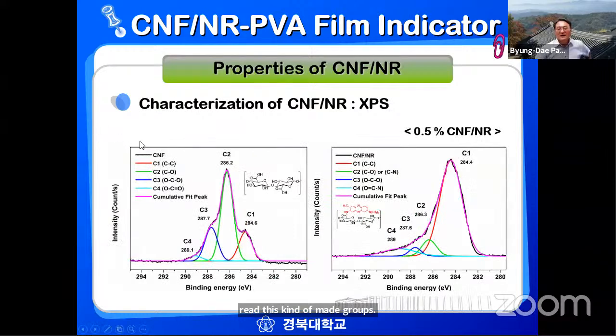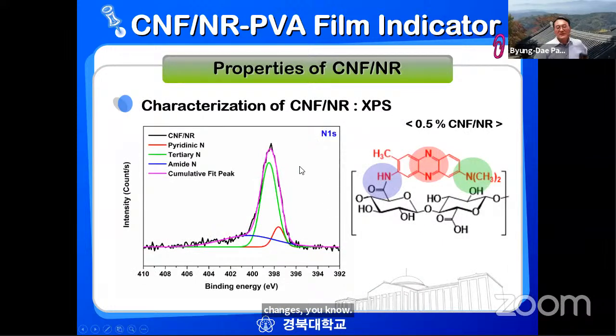And also we did the CNF XPS, the different C1s, C2, this kind of analysis. This is the control. This is the CNF neutral red composite, 0.5% composite, and then we have this kind of shift changes. And also, obviously, we have nitrogen peaks for the composite CNF and neutral red composite materials. Here, we have three different types of nitrogen environment, I would say. First is right here, pyridine nitrogen, and the tertiary nitrogen here, and then amide nitrogen here. So this is the cumulative curve. That means XPS clearly shows the nitrogen part, and also shows the amide bond between the nanocellulose and the neutral red.